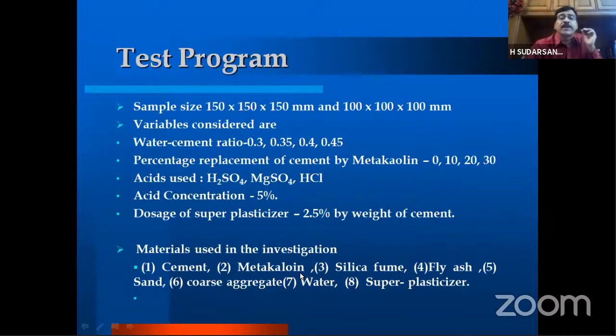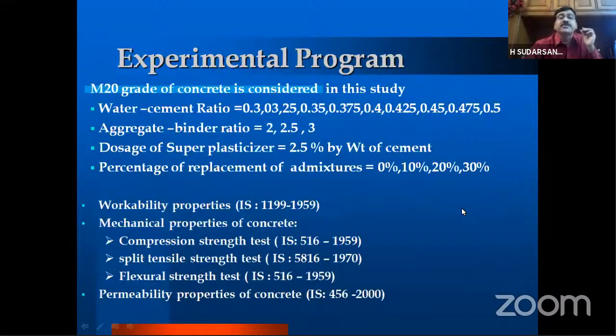So this is the test program we have used. We have used cement, metakaolin, silica fume and fly ash. Metakaolin, silica fume, and fly ash are the mineral admixtures. And we have also used superplasticizer for reducing the water cement ratio. So these are the various properties of the materials. I'll just quickly go through.